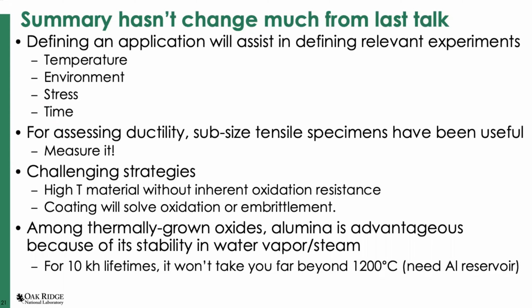I didn't get into this too much, but if you think about it, you still have to have a reservoir of aluminum in your coating or in your alloy in order to form that. And really, if you look at the numbers, some of the studies that NASA's done, when you start talking about 10,000 hour lifetimes, you're not going to go far beyond 1200 degrees C with any kind of coating. So you should just understand, none of the oxides are slow enough growing to really sustain long-term behavior at very high temperatures. So thank you.